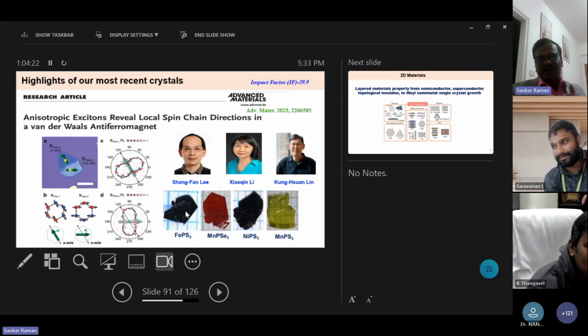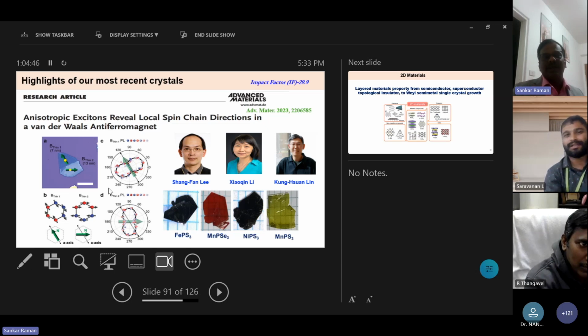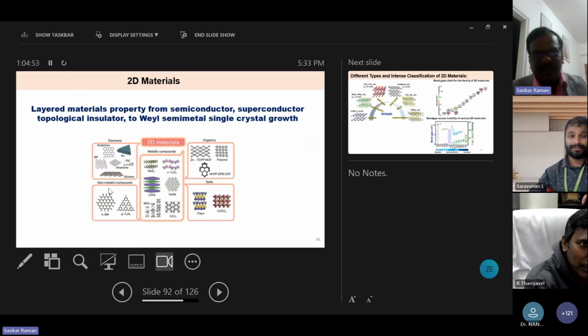And also the defect for sulfur creates a local spin chain direction. You can clearly see in the first figure the spin direction is totally different, in the opposite direction. We found that, then we did PL and second harmonic generation, everything. We are the first group to demonstrate the defect producing different local spin. Then we published in Advanced Materials. Almost this is a 29.9 impact factor paper. Then maybe I can stop here.